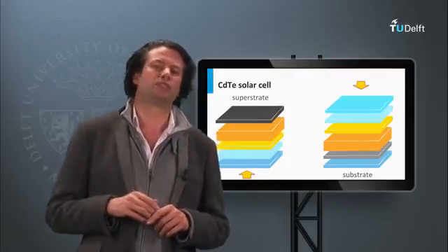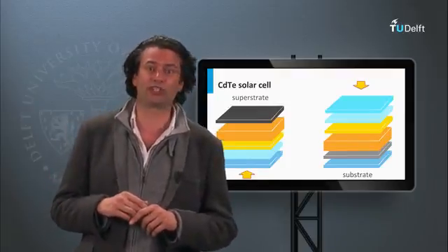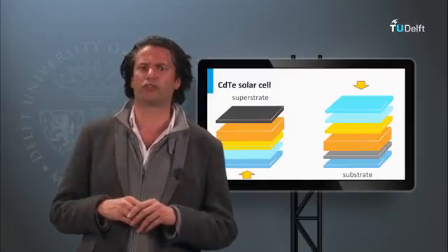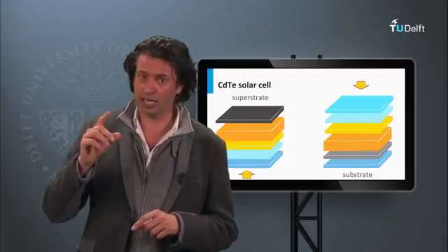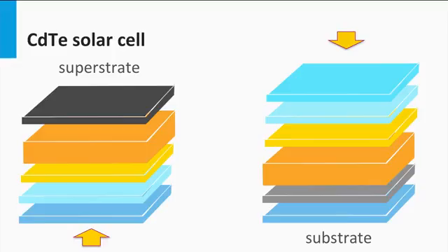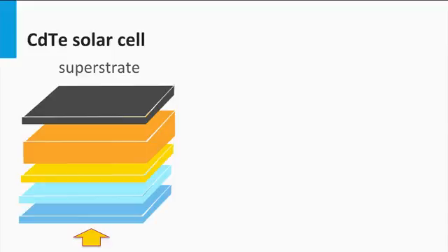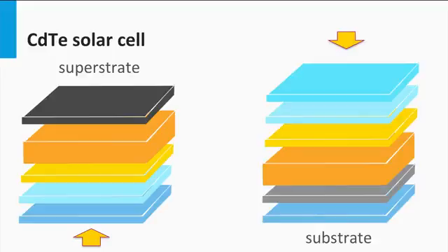An important concept I did not discuss for the thin film solar cells is the 2 types of solar cell configurations, the superstrate and the substrate configuration. A superstrate configuration is a cell concept in which the substrate on which the solar cell is processed acts as the front window at which the light enters the solar cell. A substrate configuration is that either the substrate acts like a back contact or the back contact is deposited on the substrate. Consequently, no light will pass through the substrate.